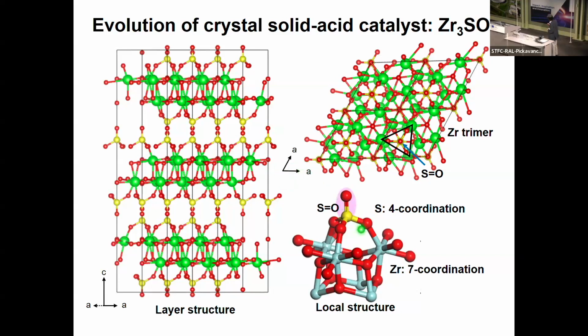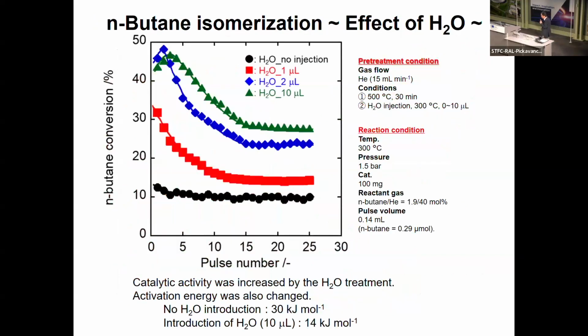Again, the material shows 7 coordinations around zirconium, and an SO bond here, and S has 4 coordinations. This is an isolated structure. So we can predict the real active site on the basis of this structure determined by the structure analysis. The one thing I have to say here now is that water plays a crucial role in the course of acid type reactions.